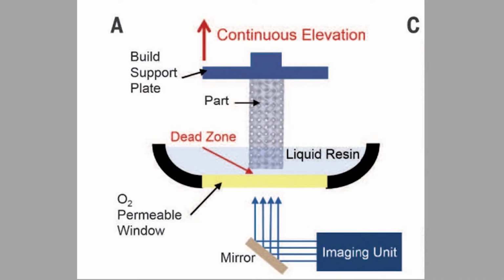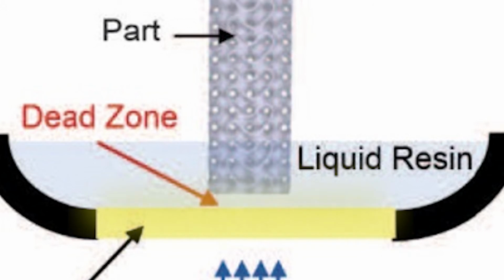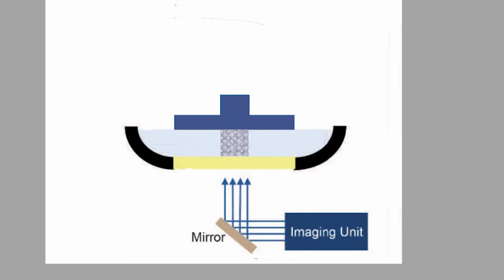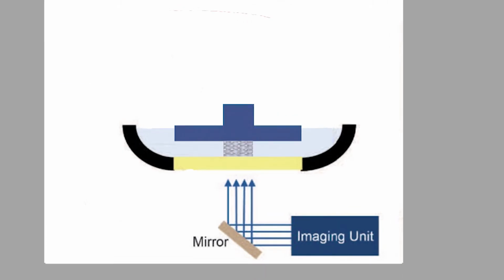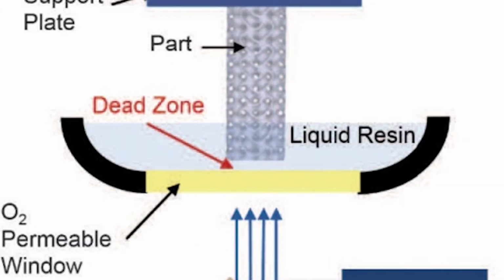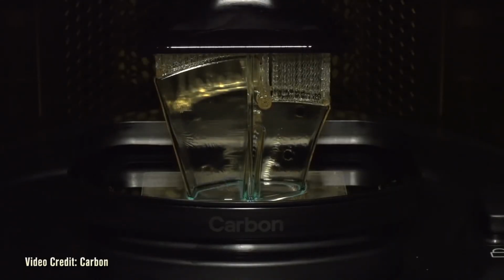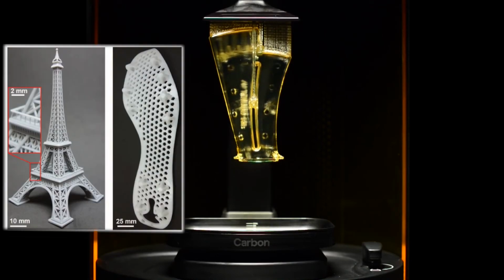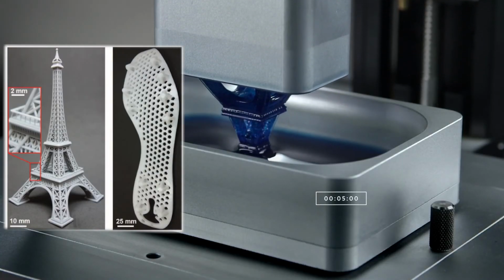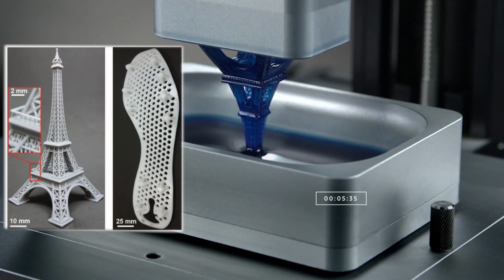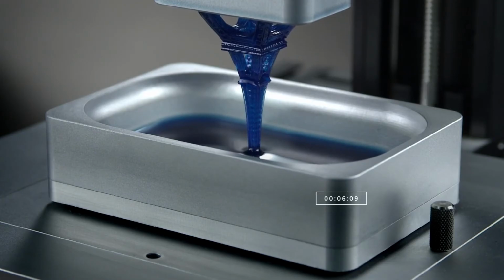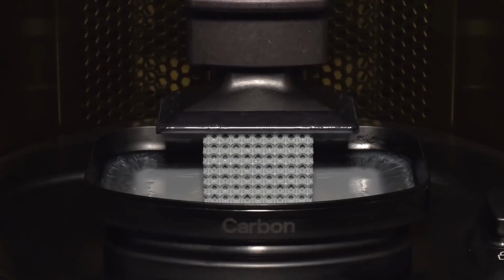The window is actually permeable to oxygen, letting a small amount of it diffuse into the solution, which builds a concentration gradient away from the window. The submerged printing platform is lowered until just above the window, where the oxygen present below the platform around the window prevents polymerization by quenching all of the radicals in the so-called dead zone. This means no polymers form on the window, which would block the light. Instead, the polymerization only occurs on the printing platform. As the plastic begins to thicken, the platform is raised, extruding its shape. If we now change the UV pattern, the changed extrusion will give us dynamic shapes and finally our finished product.